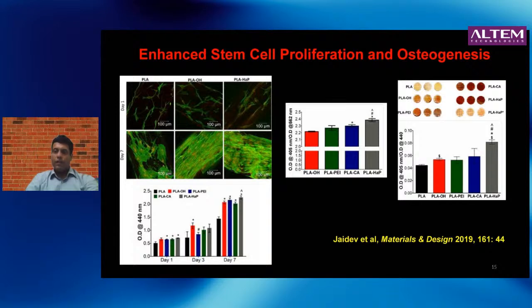And also, if you look at the amount of calcium phosphate that's deposited, you can see here that the one with hydroxyapatite coating has the most amount of mineral deposit on it. It looks dark red in color. Okay, and that's quantified here in this bar graph.